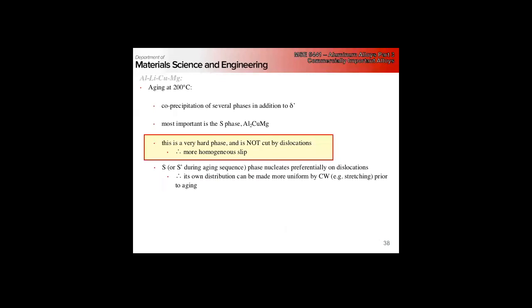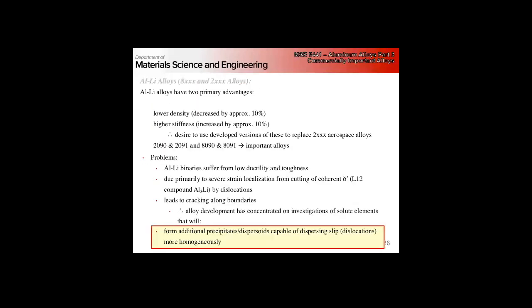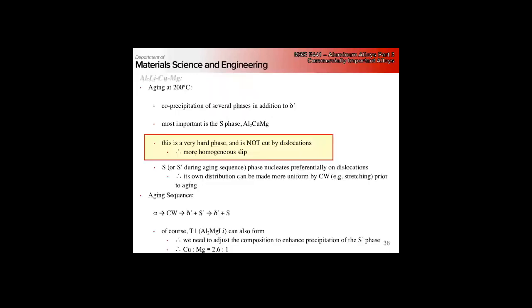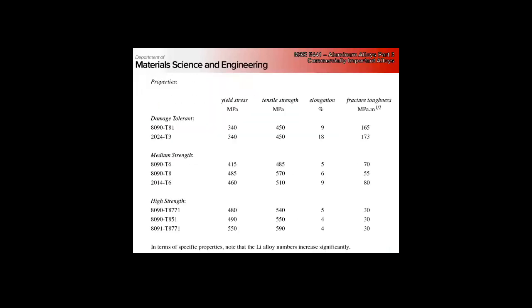And for aluminum lithium, where the additional modulus effects come from: we're making a composite with all these different intermetallics in there, and the intermetallics are stiffer than the aluminum. So overall, we end up with a higher modulus, plus if we add solid solution effects to it.